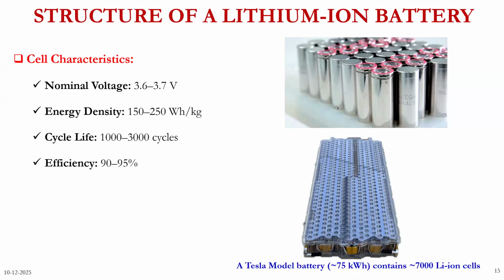It will be around 3.3 to 3.4 volts, which is called the cutoff voltage. Beyond this cutoff voltage of 3.4 volts, you should not discharge the battery further. At this point, automatically all the loads will be disconnected, so your mobile will get automatically switched off after it reaches 0% state of charge. Similarly, the upper limit we call the maximum charge voltage. Beyond that maximum voltage, we should not charge your battery. So nominal voltage is 3.6 volts. Maximum voltage is around 3.75 to 3.9 volts. The minimum voltage, beyond which it should not discharge, is around 3.3 to 3.4 volts. So this is what the battery limits are.